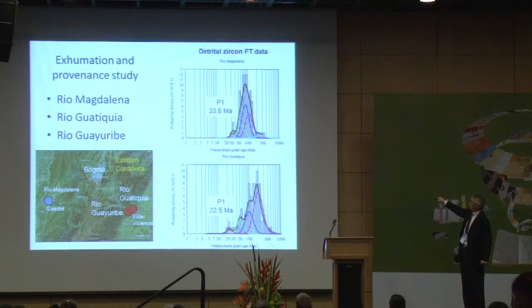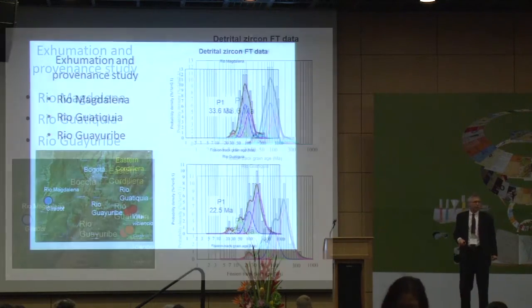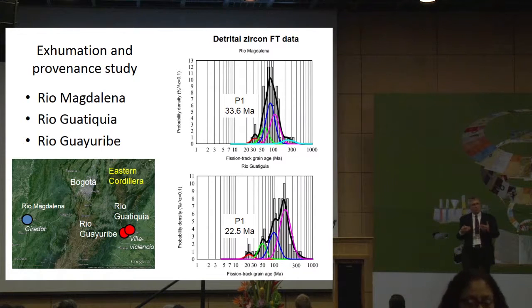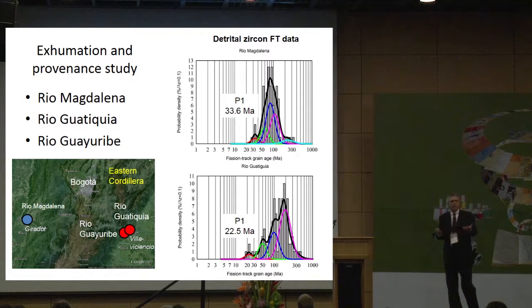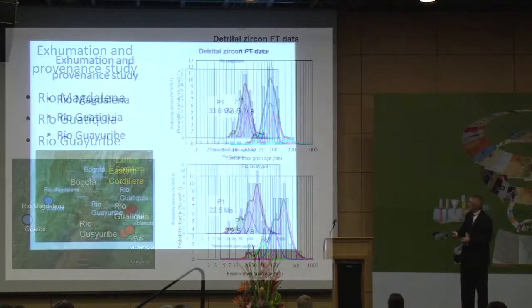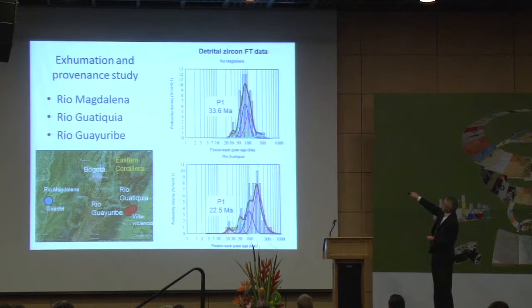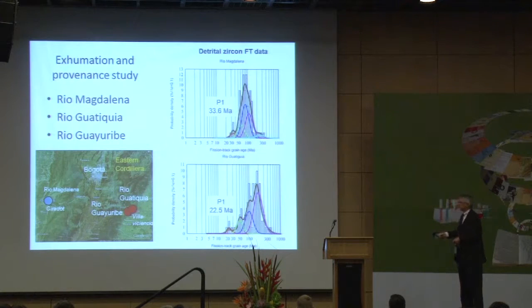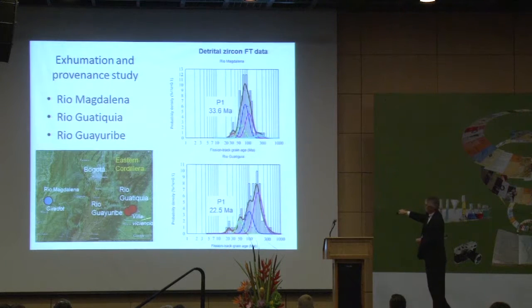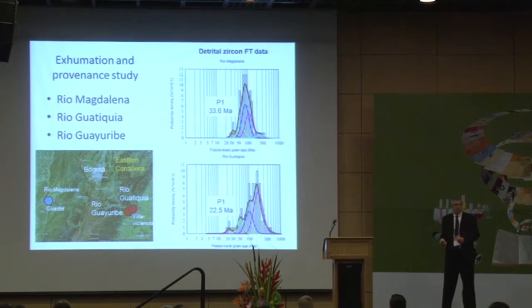And we just want to focus on the first one, which I call P1, the first peak, the youngest peak, because this is the most indicative of exhumation in the drainage area, because these zircons are derived from the areas that exhume the fastest. As you can see here, the youngest peak in the Rio Magdalena is about 33.6 million years, plus or minus 10%. And the youngest peak here from the Rio Guatiquia is about 22.5, so it's about 10 million years younger.